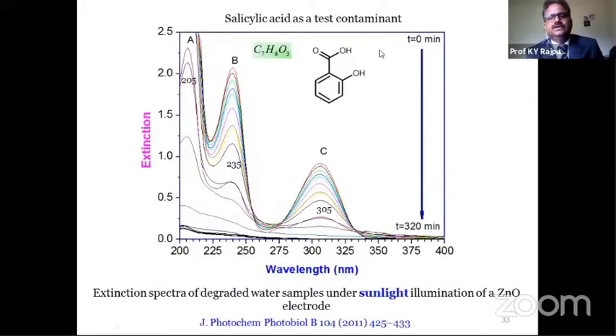These are the results on the extinction spectra of the degraded water sample. One dummy pollutant was taken, salicylic acid, and it was dissolved in water, and this water was circulated through the reactor, and at continuous intervals samples were taken from the relatively pure water, and the extinction spectra of those samples were taken. It is seen that with respect to time, the intensity of these peaks A, B, and C, these are the peaks in the UV. This peak is in UV. It continuously decreases, and this is the signature of degradation of the organic compound with respect to time.